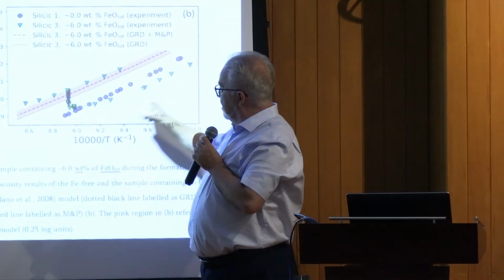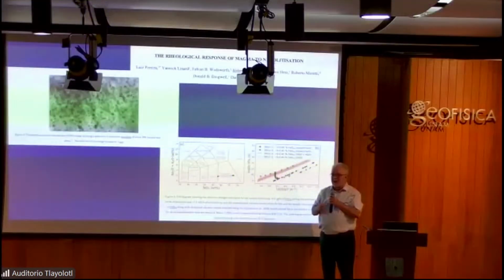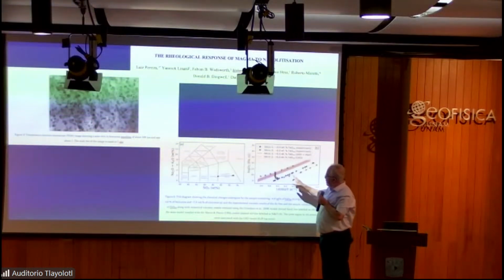So you have nanolite free, and then you just sinter the material. You force the crystallization of nanolites. Then you take a sample out again, stick it back in the viscometer and see what happened, and so on, and so on, and so on. And what we see is the viscosity rises generally with the creation of the nanolites.